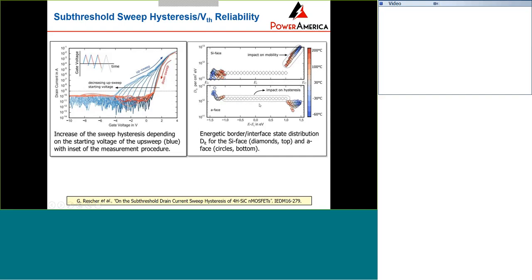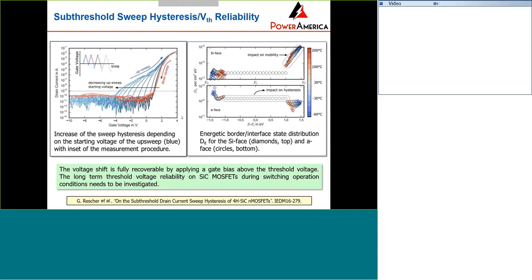Studies have shown that the a-face MOS interface has higher border traps in the mid gap of the silicon carbide band diagram, and on the contrary, the Si-face silicon carbide interface has higher interface traps near the conduction band edge. That's why the Si-face has low mobility but much smaller, very stable transfer curve hysteresis, and the a-face has much higher mobility, 2 to 3 times higher, but has higher hysteresis. But again, this voltage shift is fully recovered by applying a gate bias.